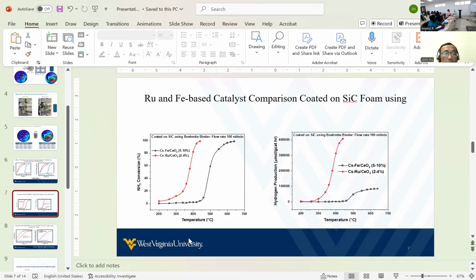So this is testing. When we do the cesium testing, I would like you to look at this coated silicon carbide. We tested cesium iron and then cesium ruthenium. So now we change the catalyst. These are two different catalysts, both on the monolithic. The cesium iron is cheaper, but the iron is slow compared with the ruthenium. You see this is ruthenium, this is iron, and this is ruthenium, and this is iron.